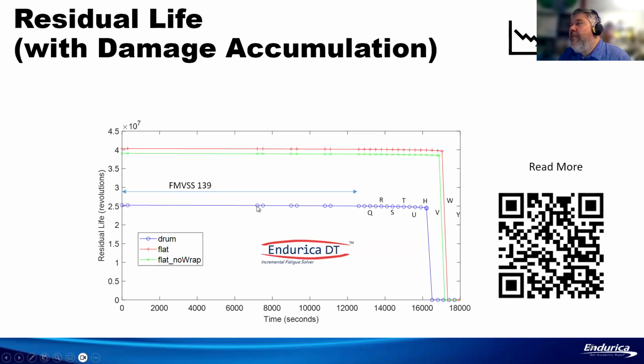And then as I keep accumulating, you can see I get to the Q step, the R, the S, the T. You start to see a slight decrement of the residual life until we pass step H, and then we go into step V, and you can see that at step V, the tire loses integrity, and we've got failure.